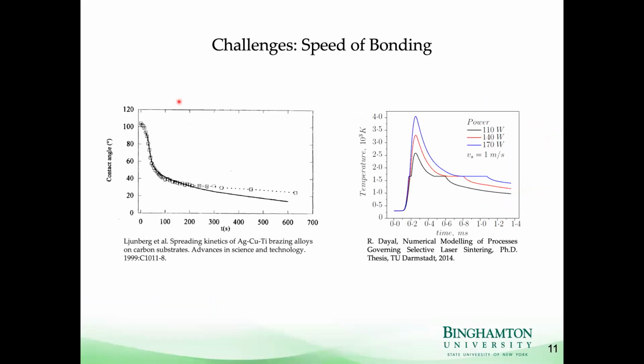So there's some challenges with printing, creating a good bond onto silicon with laser 3D printing. In conventional brazing processes to dissimilar materials, like metals onto graphite or metals onto silicon, the bonding process takes on the order of minutes. But in selective laser melting, each pixel, each little area on that print is only hot for a fraction of a second.